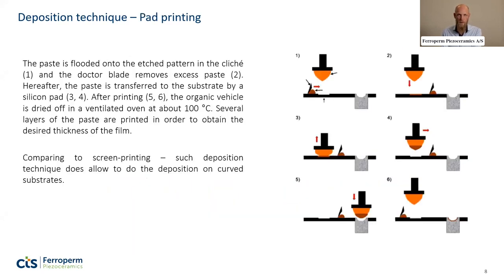An alternative process that we developed at Ferroperm is pad printing, for piezoelectric thick film. So pad printing is well known for printing graphics on curved substrates or surfaces like pens, golf balls, Christmas balls, and so on. And the way it works is that you have a steel cliché with a pattern etched into the surface, and then by scraping a doctor blade over the steel cliché and the paste, you can deposit the paste into the pattern in the cliché, and then the pattern or the paste in that pattern is transferred to whatever surface you have using a soft silicon pad.